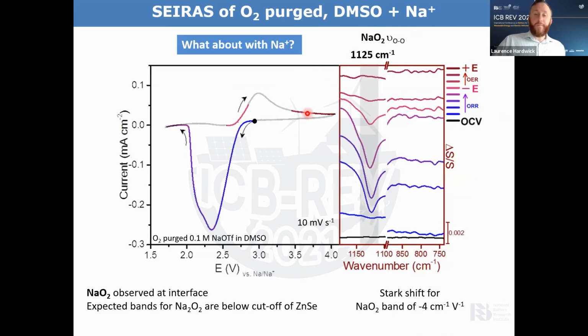And we repeated this with sodium, so a sodium oxygen battery, and we have our flat spectrum here. As we switch this potential, we see that we have a negative growing peak, which can be assigned to sodium superoxide, and we can fully oxidize this system without oxidizing our gold electrode. As we sweep back again, you can see that we again return to this flat part here, showing that we've completely removed our sodium superoxide from the surface.